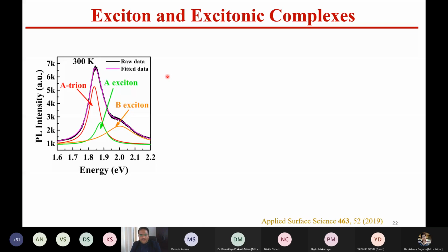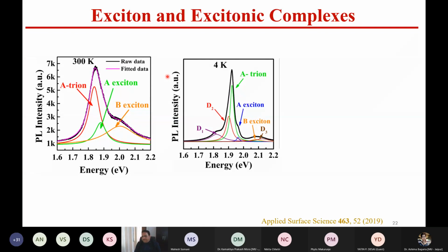So what we have done is build up our understanding by doing the low temperature Raman as well as the PL spectroscopy. This is the general understanding: at 300 Kelvin, you have an A- trion, an A exciton and a B exciton. That's all that people report.